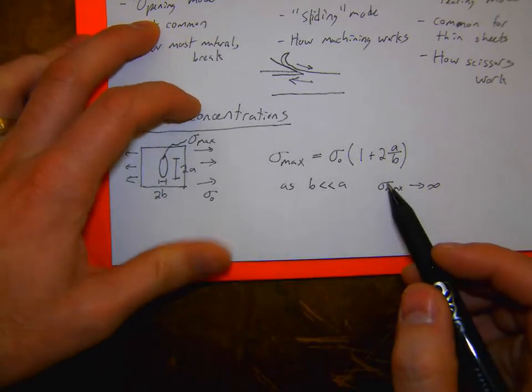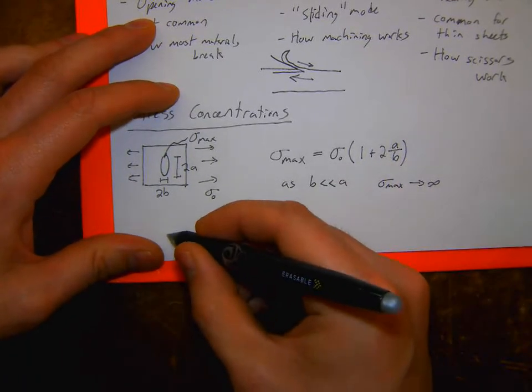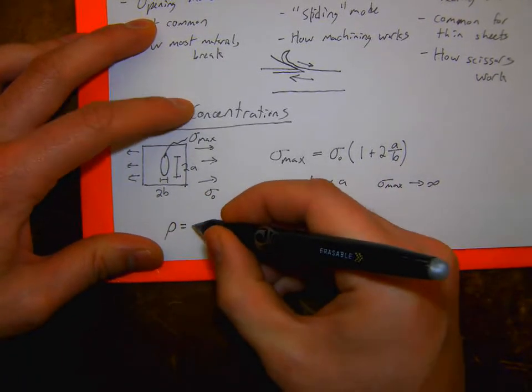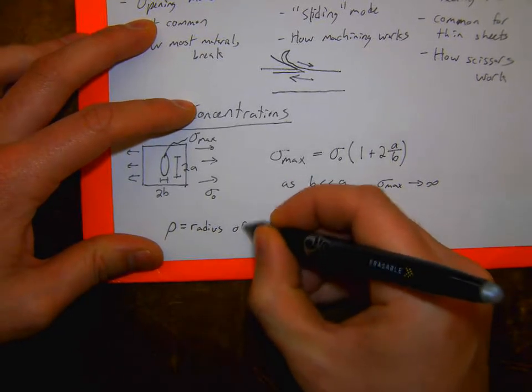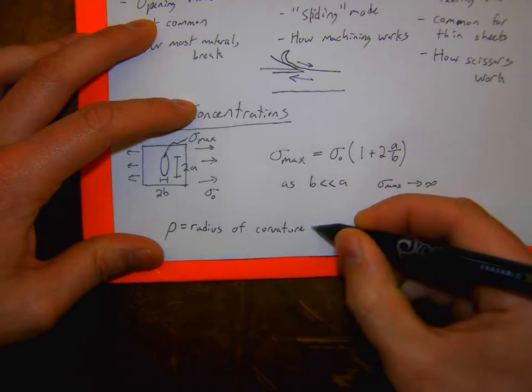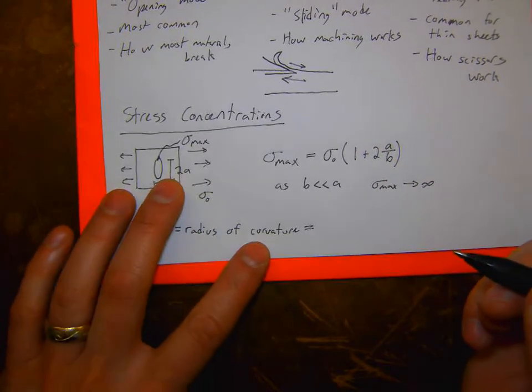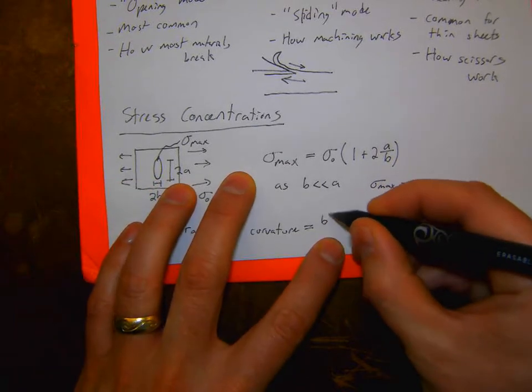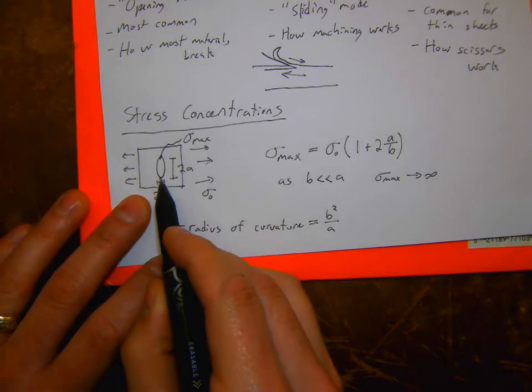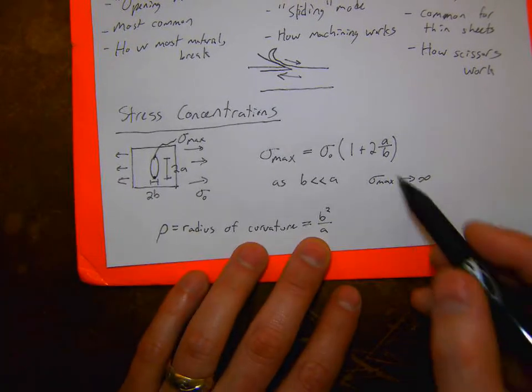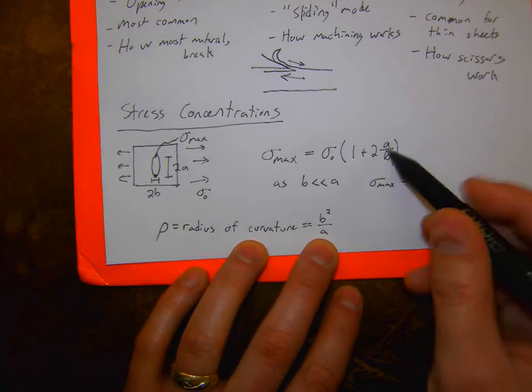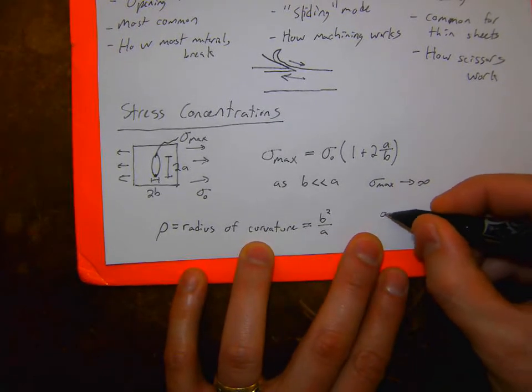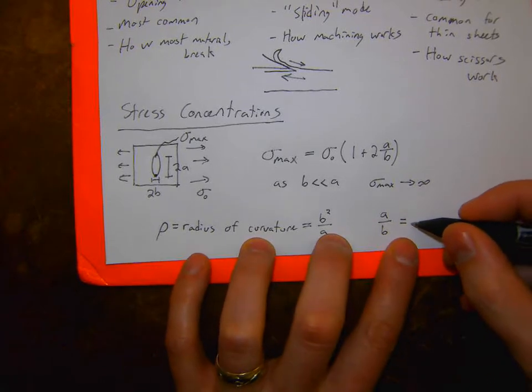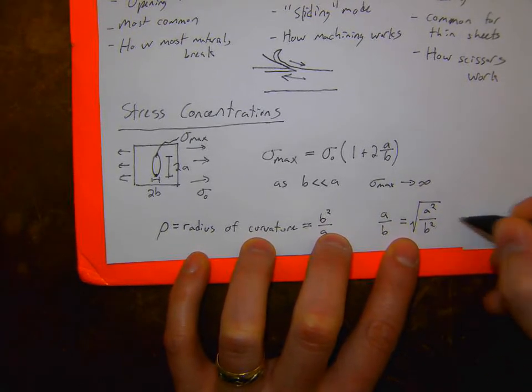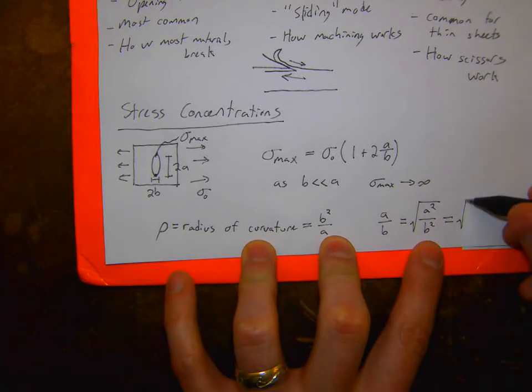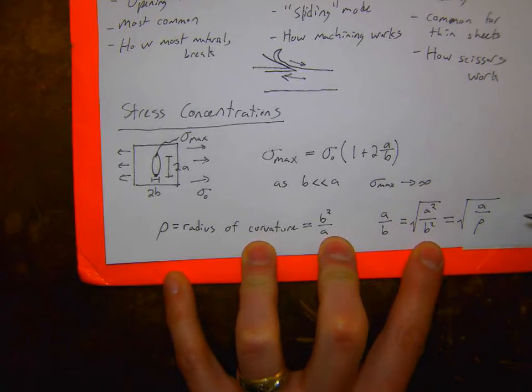So what we're going to look at instead is the radius of curvature at the notch, and I'm going to rewrite this equation using that. I can define a constant, rho, which is the radius of curvature, which is b squared over a, at this corner of the ellipse. And so I can use that to replace my a over b. a over b is also equal to the square root of a squared over b squared, and replacing that b squared over a, this is the square root of a over rho.